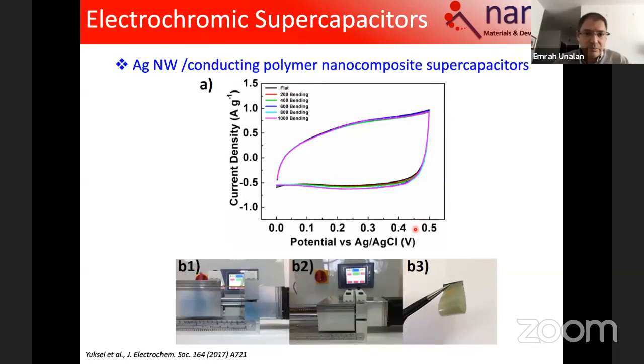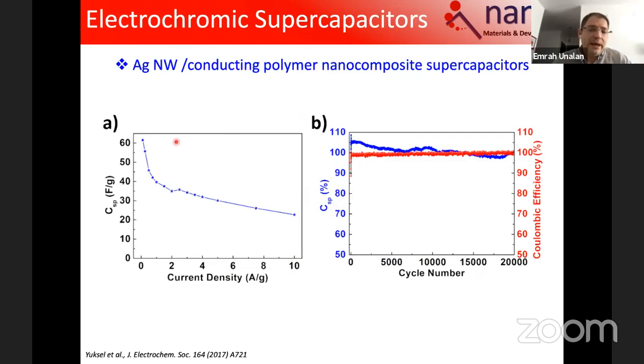And these things are on plastic substrates, right? So these things are very flexible. And the storage characteristics, as you see, don't really change with the number of bending cycles. And the capacitance is low. That is one of the problems associated with the polymers. Nothing can be done on that, but it gives you some other benefits like flexibility. And on the right-hand side, as you see, these materials can be cycled, in this particular example, for 20,000 times with no change in the specific capacitance. And I surely believe that we could even go longer. So they are very stable storage materials.